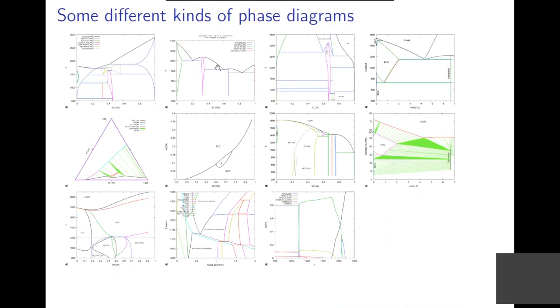These are typically binary diagrams: iron-molybdenum, manganese-copper, magnesium-copper, uranium-oxygen. This is iron-carbon, both the stable diagram and the metastable one with cementite. A ternary diagram, iron-chromium-nickel. And the one nice thing with Thermo-Calc and OpenCalphad is that you can calculate a diagram like this, and then you can plot it like this.